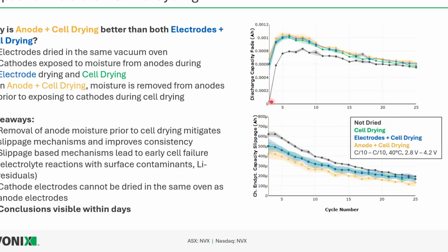Yeah, sure. A lot of the time, especially when we're doing very apples to apples comparisons, we're not changing cathode materials or anode materials between these comparisons. What we see is these trends continue more or less. If we were able to measure these infinitely accurately and precisely, we would see these trends continue together. With UHPC, of course, there is going to be a limit, and especially the consistency between the cells will reach a limit at which these all more or less within error coalesce. But the reality of UHPC testing is these channels are a lot more expensive than other channels. So we really try to tailor what tests we do on here and do these kind of rapid screening tests where I show 25 cycles here.